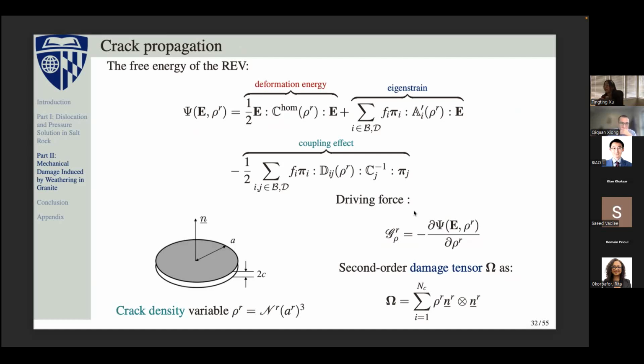So here in this free energy of the REV, you can see that we generally have three terms. The first term is the traditional term, which defines the deformation energy. And here C homogenized is the homogenized stiffness tensor, and E is the global strain tensor. The second term is the eigenstrain, which defines the contribution from this biotite expansion under the weathering. And the third term is actually the coupling effect. So it tells us how the crack propagation and the weathering are coupled with each other.